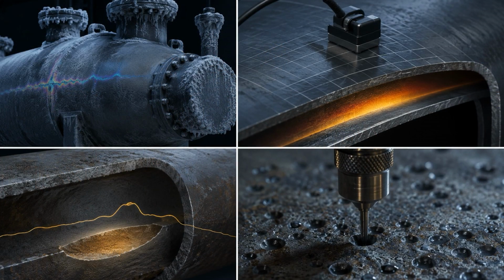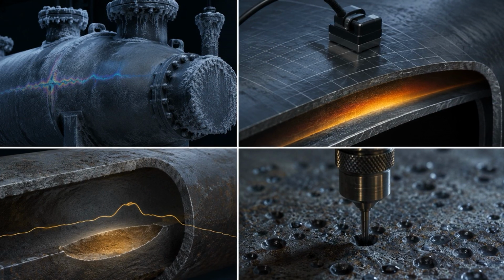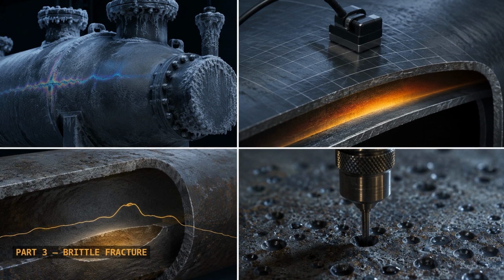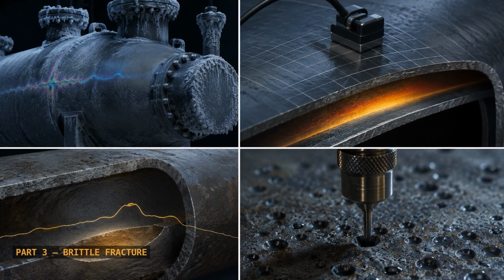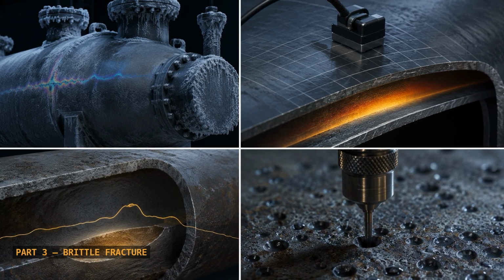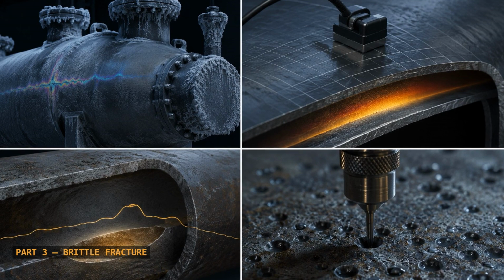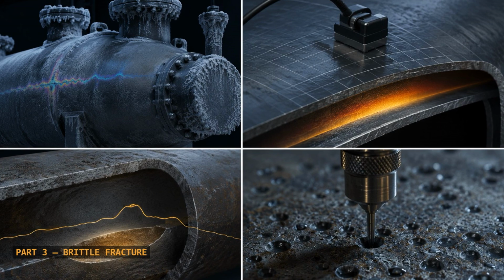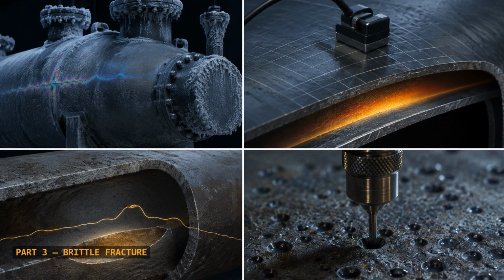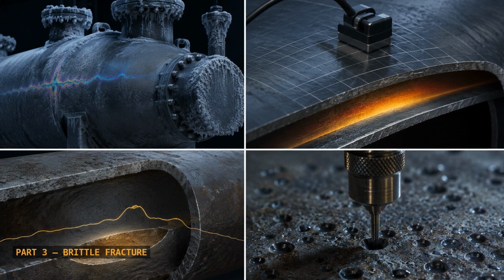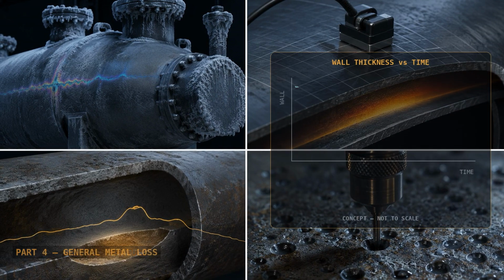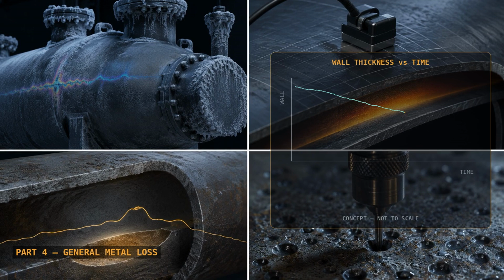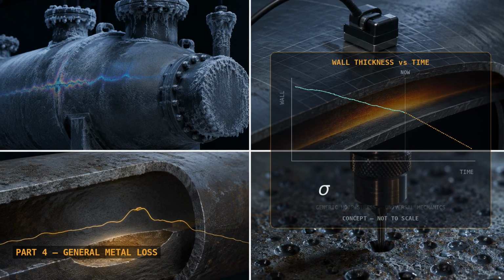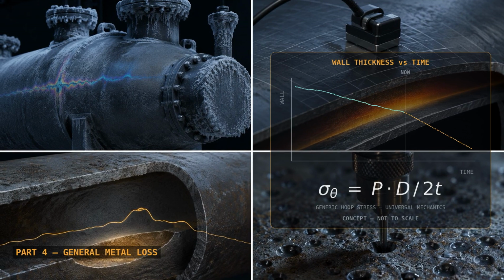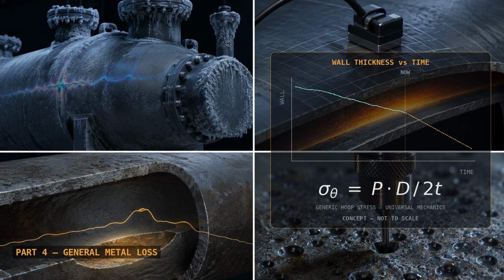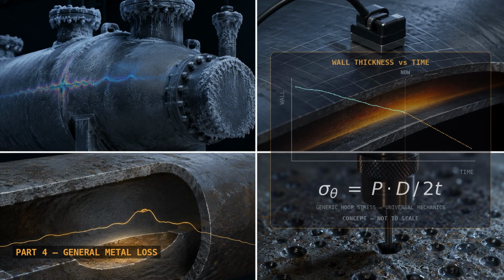The standard is organized by damage mechanism. Each part answers one specific question. Part 3. Brittle fracture. The risk that older, thicker, lower toughness steel fractures at low temperature during startup, shutdown, hydrotest, or auto refrigeration. Usually this isn't an inspection find. It comes from comparing operating temperatures against material toughness. The question: is there enough fracture resistance at the coldest temperature and highest stress the equipment will actually see? Part 4. General metal loss. Broad, fairly uniform corrosion or erosion across a large region, found by ultrasonic thickness grids and profile radiography. The question: with allowance for future corrosion, is the average remaining wall still thick enough for the loads?